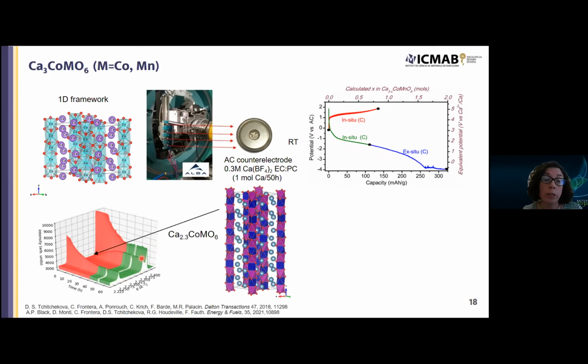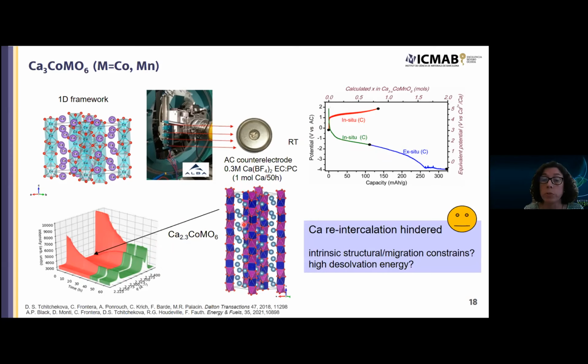So the thing is that we were able to elucidate the crystal structure of the oxidized phase, and we were able to refine the amount of the occupation of calcium. And it's clear that we have electrochemically extracted calcium from the crystal structure, but somehow this does not seem to be reversible. So this can be due to intrinsic structural constraints.